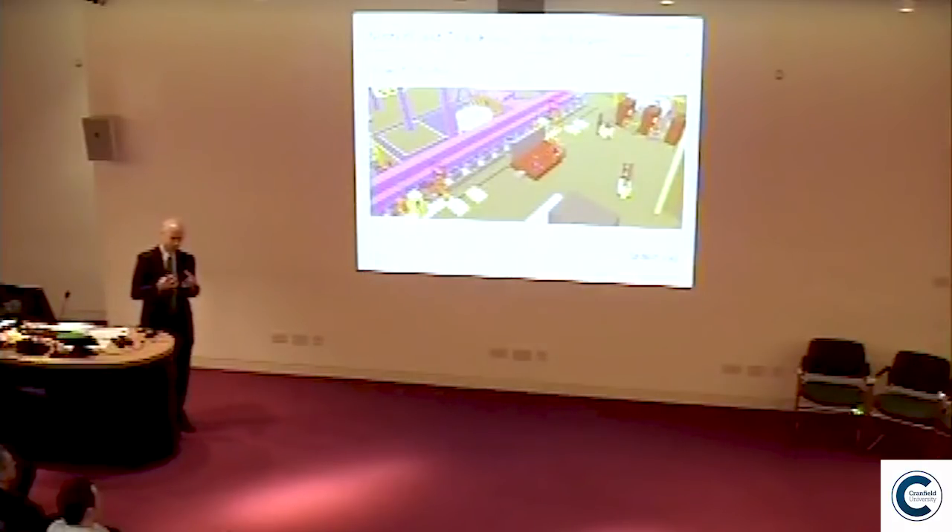From the correction steps it comes to a temperature measuring platform, then normal chemistry sampling, and then from either one of two pouring cars — all normal stuff for a cast iron foundry. It's rather busy though. We make two cylinder blocks on this line: a 50-kilogram cylinder block and a 135-kilogram block. The small one is made from a 1,400-kilo ladle and the large one from an 1,800-kilo ladle, with five ladles in the run at any one time. We produce between 18 and 20 ladles per hour.